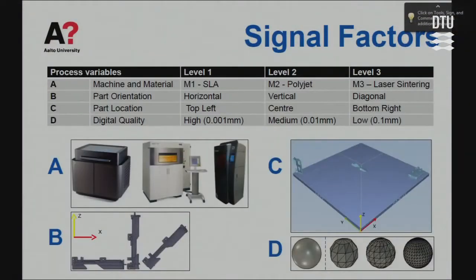So if I move on, I started planning the design of experiment. I used these 4 process parameters with 3 levels each. For the machine and material, I used 3 different machines, which are the most promising technologies for plastic processing. I used SLA technology, which is this machine, a 3D Systems stereolithography machine. I used PolyJet technology, which uses printer heads. It's a different technology, with a photocurable resin. And I used laser sintering, which is powder and a laser sintering the powder layer by layer. So these are the 3 levels for the first process parameter.